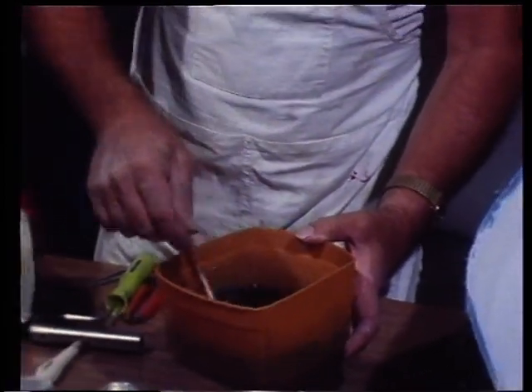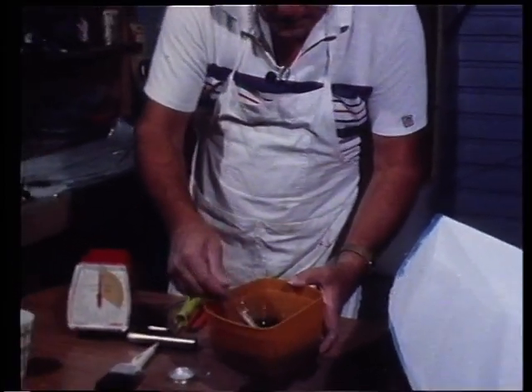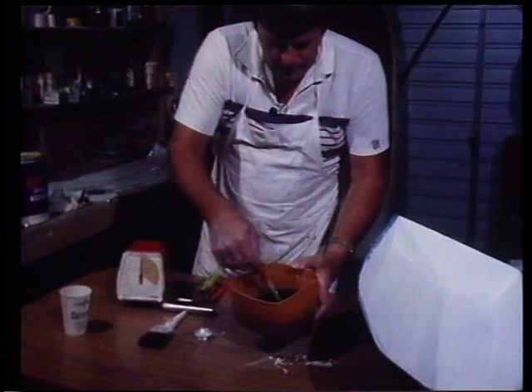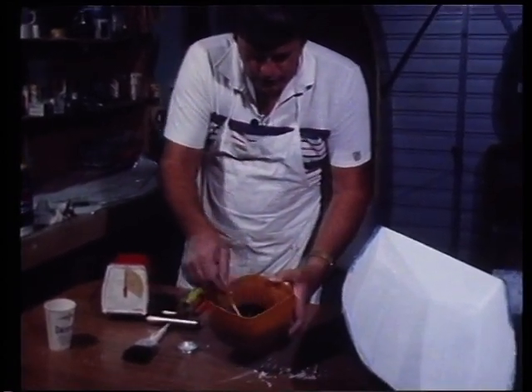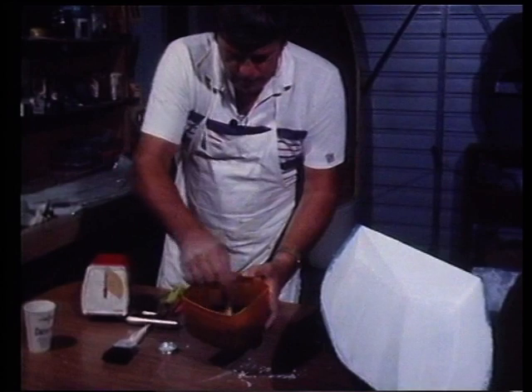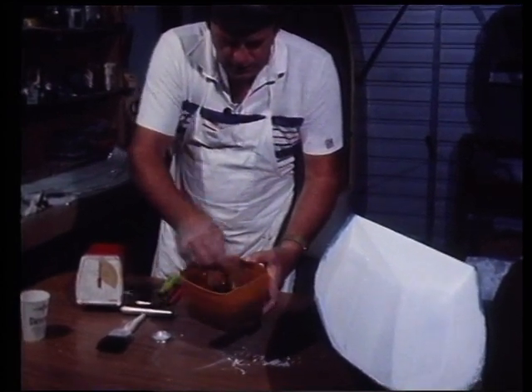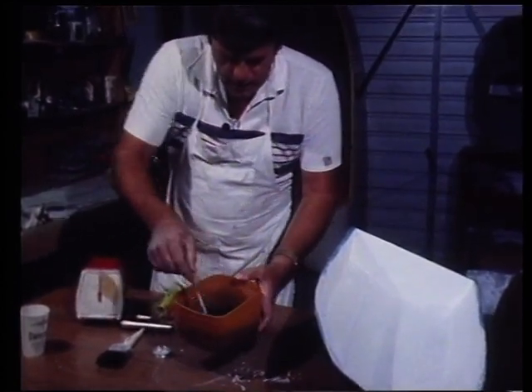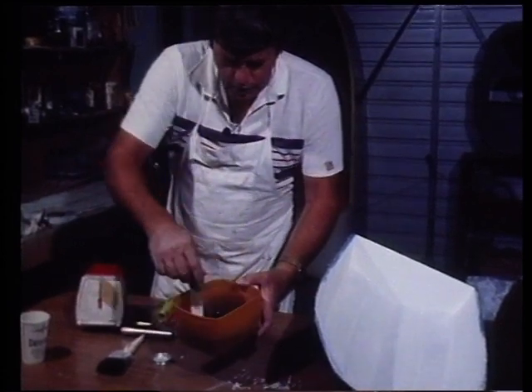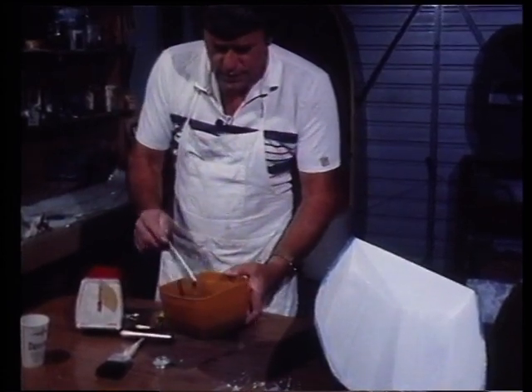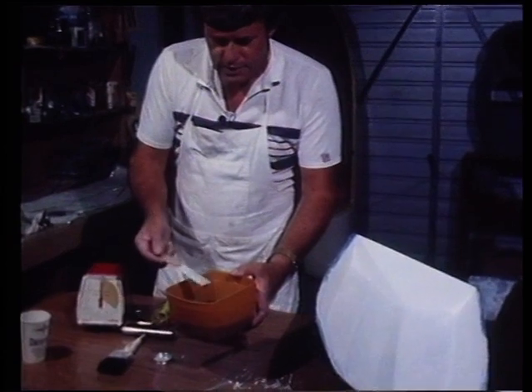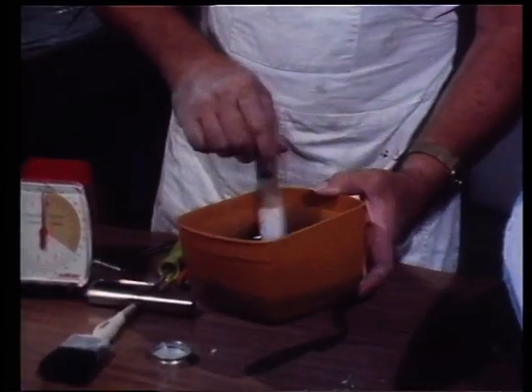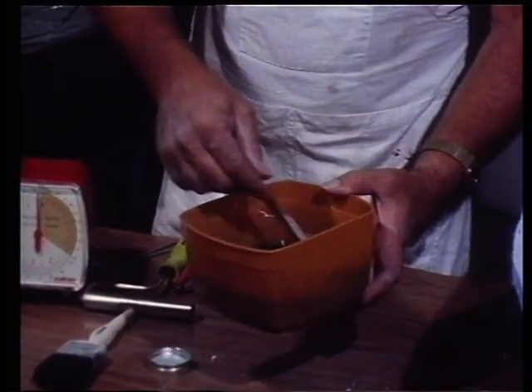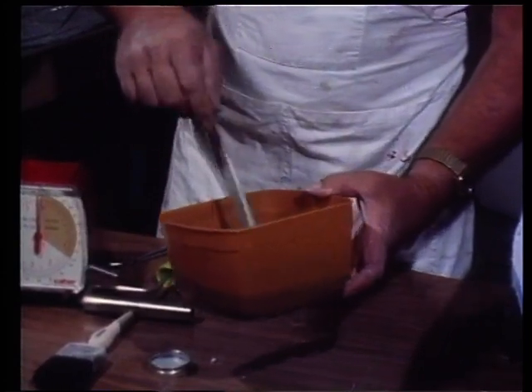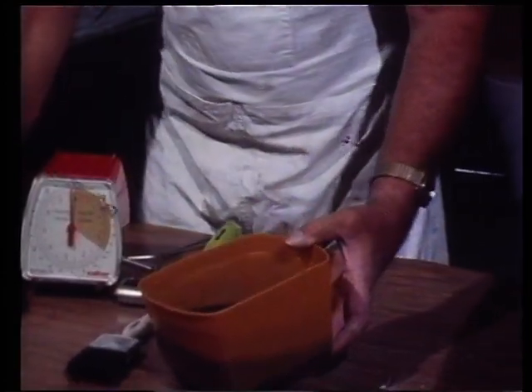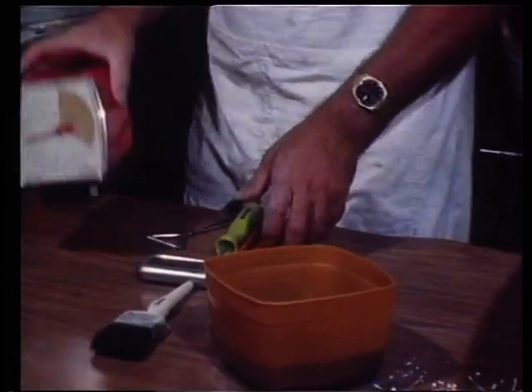Now, I'm stirring that, agitating it quite well, but I'm not beating it because I want to eliminate the amount of air that I actually introduce into the resin by stirring it, making sure that I scrape the sides and the bottom of the container with the stirring stick, and just making sure that that really is stirred properly. In fact, a stirring stick of that size and shape is ideal. You'll notice that it's fairly flat and thin. It's like a paddle, and it really does agitate the resin around there. Now, I'm satisfied that I've got that well enough stirred, so I'll just put all that aside, including the scales,